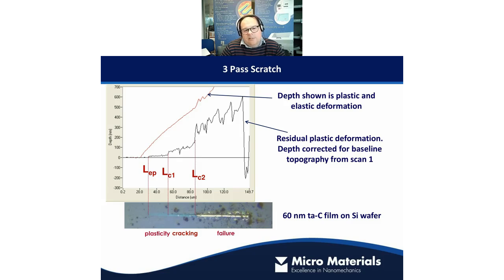Then we see this other fairly clear transition point here, quite a major step. This is where we start to get some film removal behind the probe. We see it's behind the probe because we see no corresponding event in our loaded pass. During the loaded pass of the scratch test, there's no obvious sign of anything happening. But when we do that post-scratch topography, we can see that we've actually started to achieve some film removal. So there's a step here. That's telling us that we've got some kind of failure behind the probe in this case. That doesn't always happen. It depends on the nature of the sample.